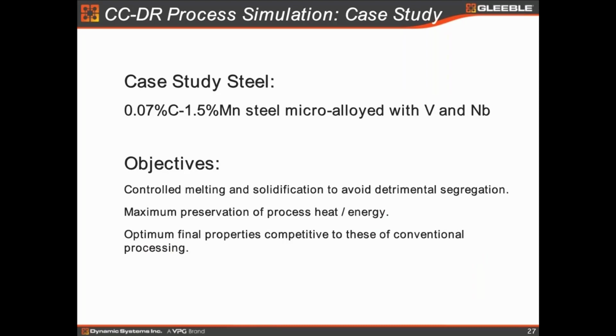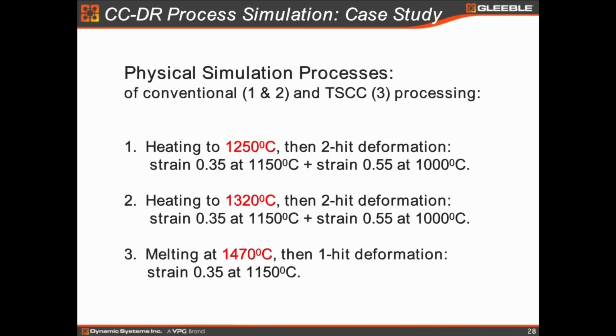this simulator can simulate all kinds of casting procedures. This machine can actually, as a feature, shift the specimen longitudinally. In other words, you don't have to deform in the melting zone. You can shift the sample sidewise to deform in a different zone. That's possible. But I want to make a case study for a low carbon steel, 0.07 carbon with 1.5 manganese, micro-alloyed with vanadium and niobium, to do some casting deformation simulation to see the microstructure and the flow stress.